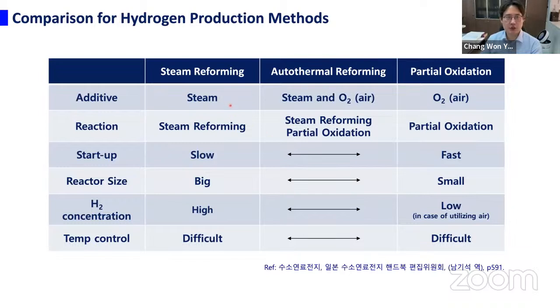Okay, so this table shows you the comparison for hydrogen production using, for example, methane here. So 3 representative processes for hydrogen production: steam reforming, POX, and autothermal reforming. If you look at the additive here, for steam reforming, steam will be added, and for POX, oxygen, actually air, will be added, and autothermal reforming adds both steam and oxygen. And startup here is slow. This is the big reactor, and the temperature is about 800 to 900, so it takes time to increase the reaction temperature. So startup is slow. The POX is so fast, and autothermal reforming is in the middle.